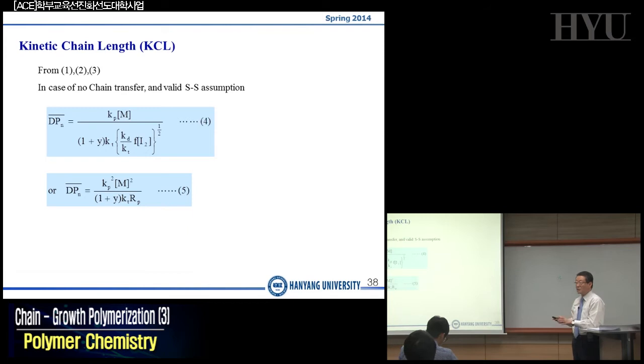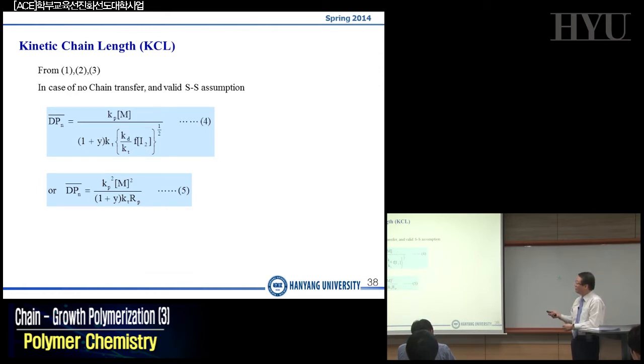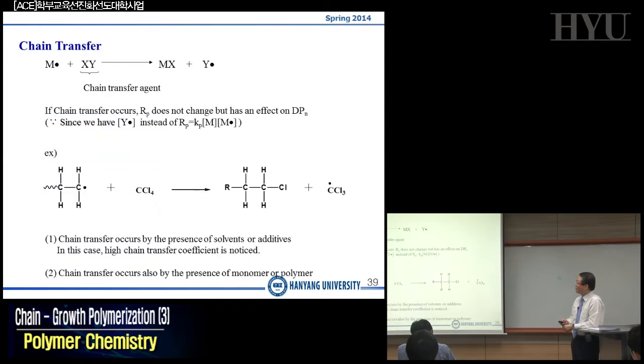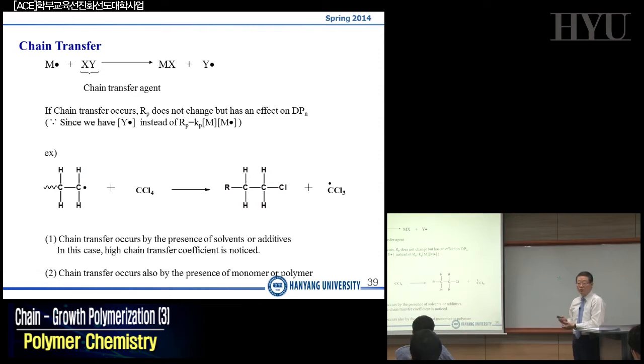In the next slide, we will look at what happens when we have chain transfer reactions, and we will modify equations 4 and 5 with the chain transfer mode. When you have a chain transfer, a growing chain with a radical at the end will meet the chain transfer agent. The chain transfer agent could be any species — could be a polymer, could be monomer, or could be any kind of solvent or additive.